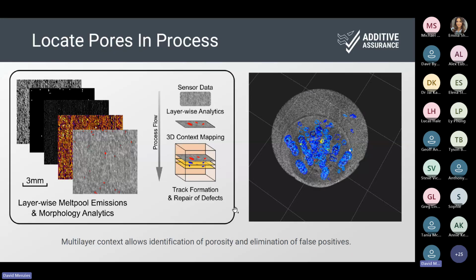I've used a PDF here as opposed to my PowerPoint. On the right, that should be a video, but I know it would crash if I was to use that version, so I've just flattened it down to a single image. It's a bit hard to see what's going on there, but there are two different colors of blue, and they are looking for pores within a test coupon that are occurring. Those pores are anywhere between 50 and 500 microns in size, and we're able to detect them with a 95% confidence down to 82 microns, which is a lot better than other techniques have reported, which is more around the 500 micron level.